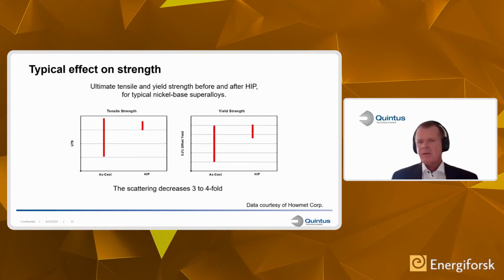You mentioned scatter, reduction of scatter. I think this shows that even though we do not see, in this particular case, an improvement in the maximum tensile and yield strength, we can definitely reduce the scatter of the test results by 3 to 4-fold. This is for a nickel-based superalloy.